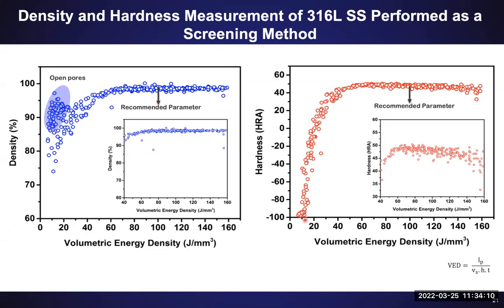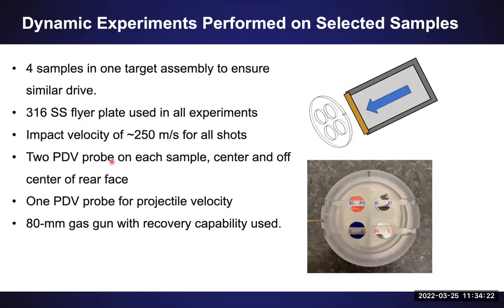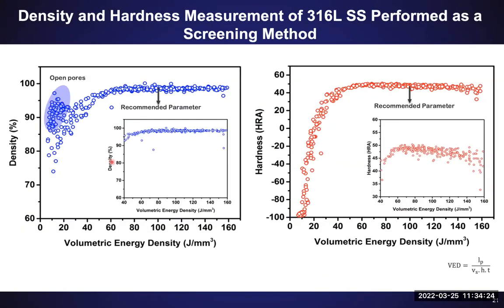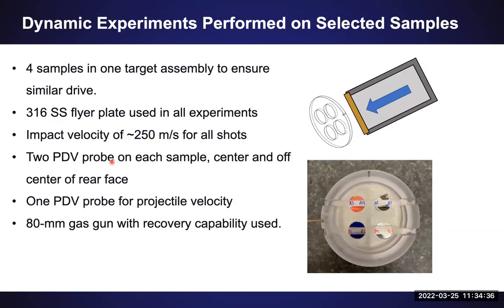Similarly, for hardness, you can see that the hardness changes quite drastically with volumetric energy density. And we again chose samples from the region where the samples had the maximum hardness possible. Using these techniques, we actually narrowed down about 9 samples for dynamic testing from about 224 samples. We then take these materials and, actually, I'm going to skip and I'll go back to that slide.